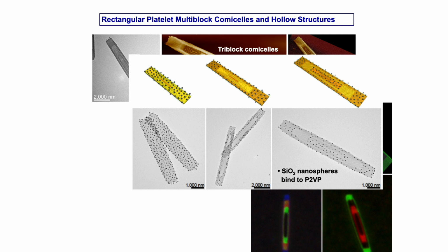You can also use a corona-forming block that, for example, will bind to nanoparticles. So you can use a corona-forming block that will bind to silica nanoparticles, and then when you add silica nanoparticles, they selectively add to those regions. So you can spatially, selectively add nanoparticles to different regions of your structures.